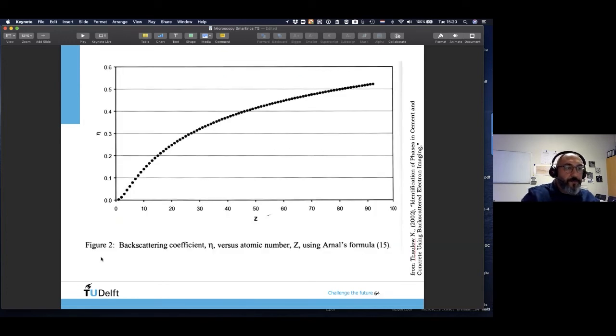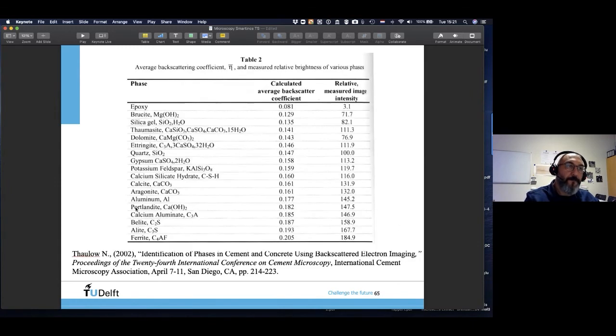You see here also the backscatter coefficient. As we increase the mean atomic number of our phase, we see the backscatter coefficient increases, which means the grayscale brightness will be higher. It will be closer to white. And for different materials or different systems, you can do this, but you see for concrete, for instance, here on the left-hand side, you see important phases, and based on their mean atomic number, you can calculate the backscatter coefficient, which can be translated into the relative measured image intensity.